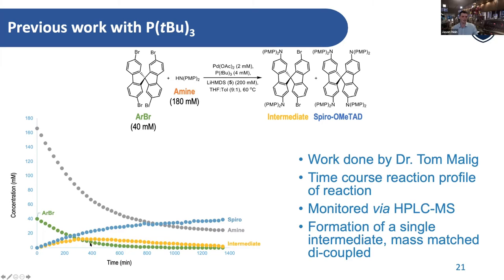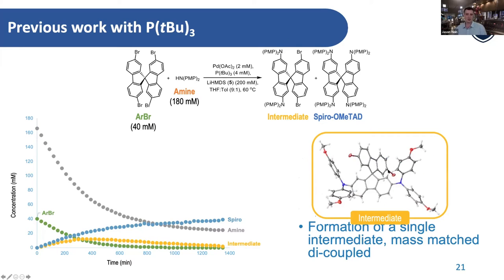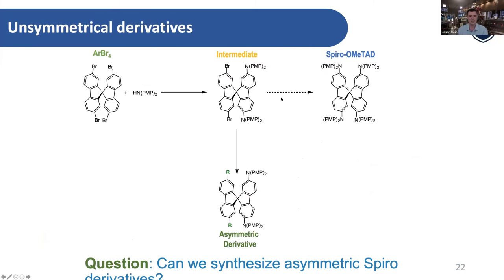Most importantly, because we only have this disubstituted one here, we knew we were getting this by mass, but actually growing the crystal structure proved that our hypothesis was correct. In fact, we're getting two substitutions across this fluorene system and no substitution across here. So it's not a case where it's doing two and pausing, it's utilizing this ring walking behavior in this way. So we wanted to leverage this further and understand it. We want to be able to go through and derivatize these things more and then look at this from a ligand perspective, if it was possible to control it.